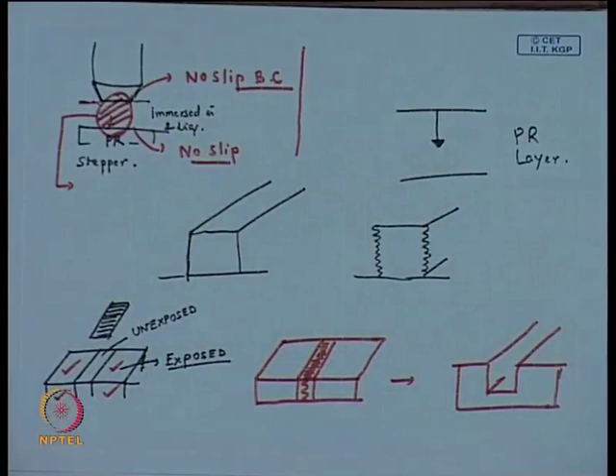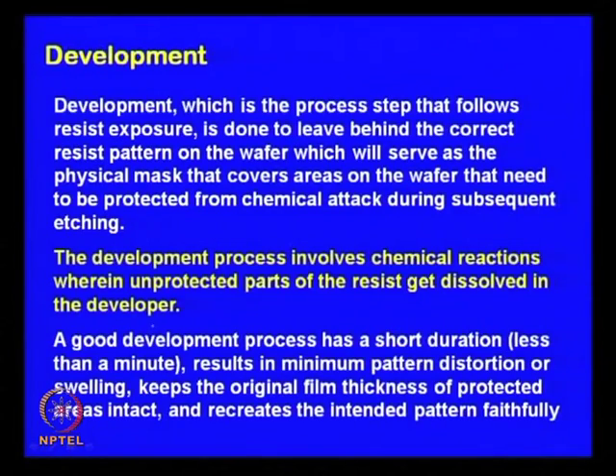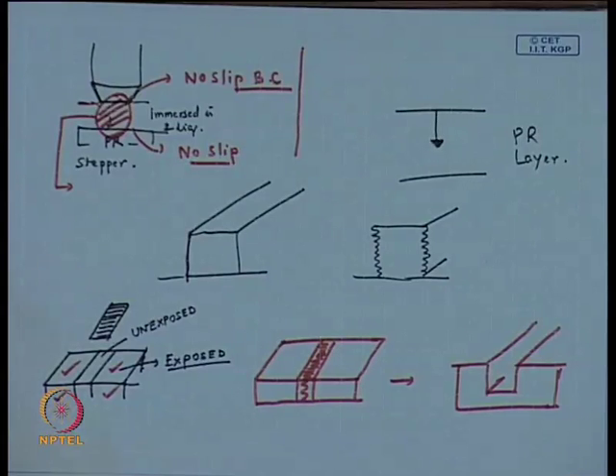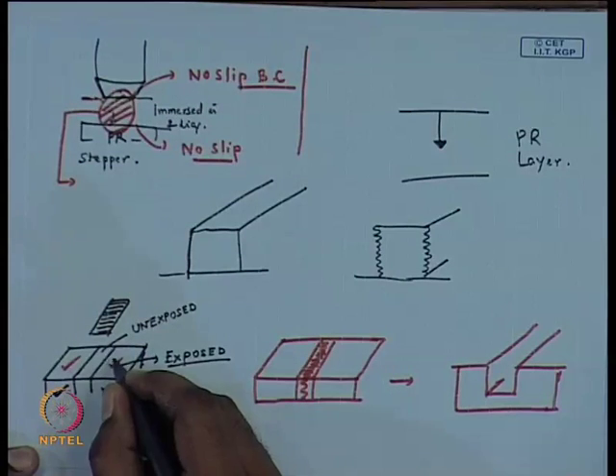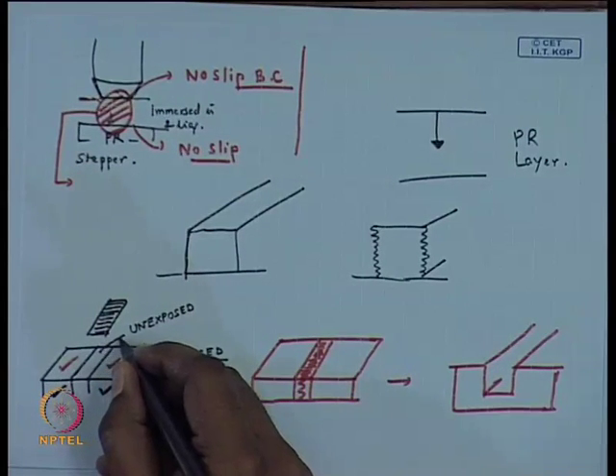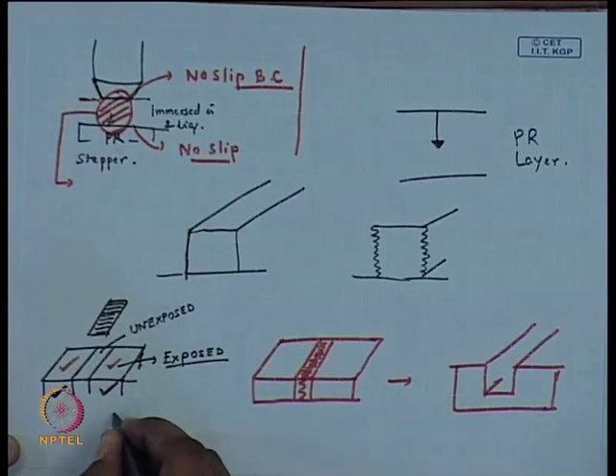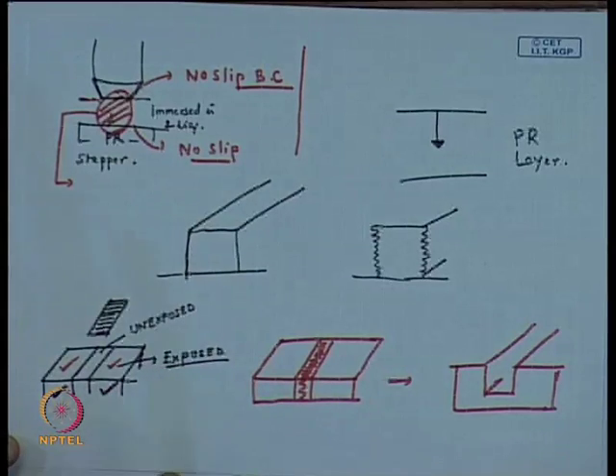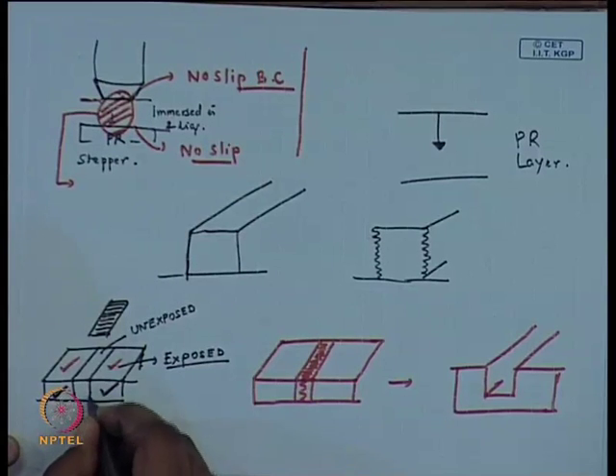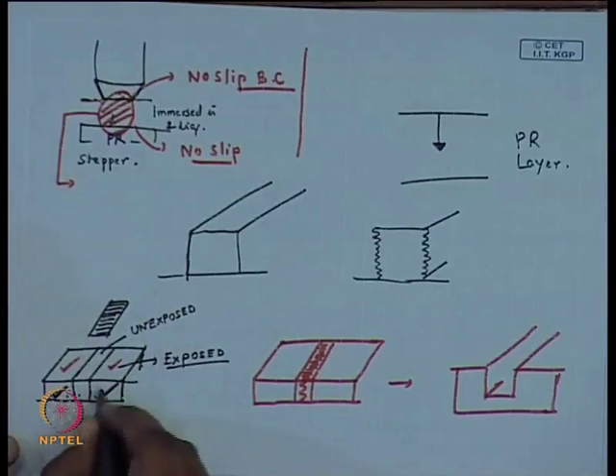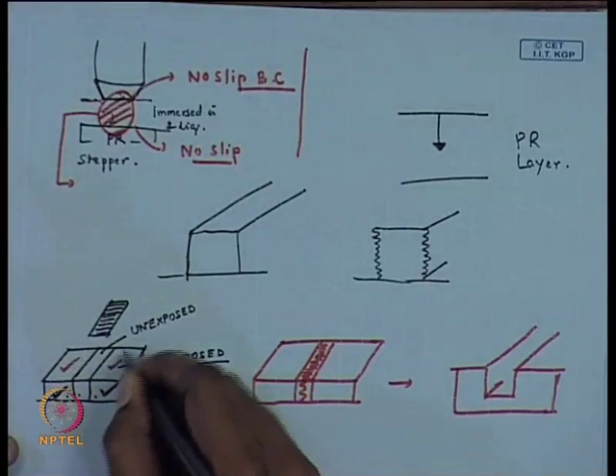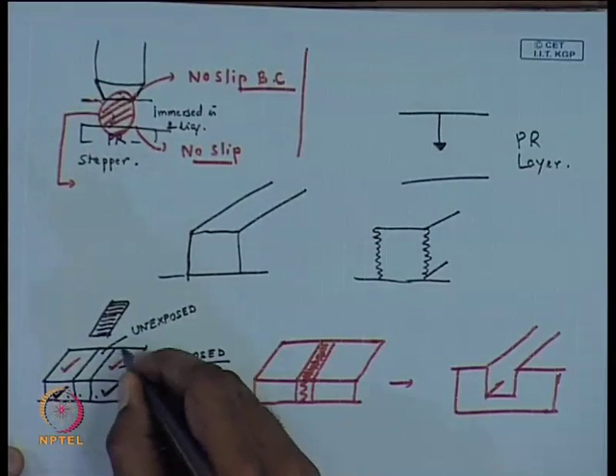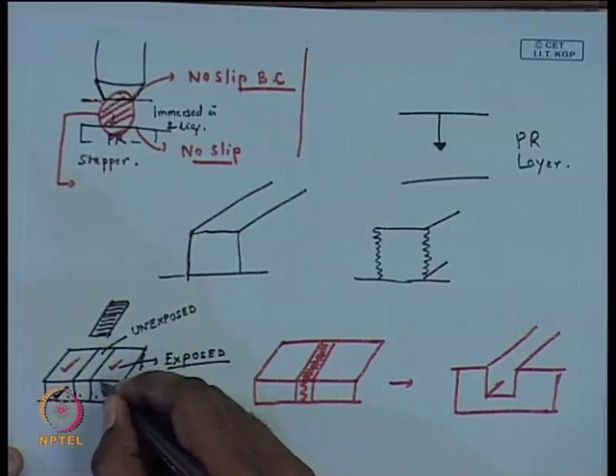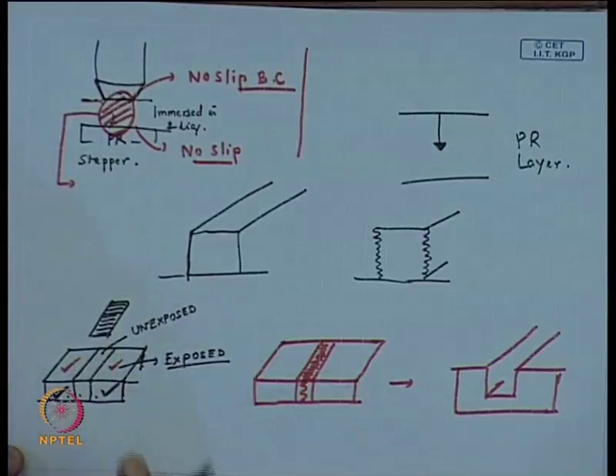There are also quite a few nitty-gritty issues associated with it. It must be understood that a good development process has a short duration, because ideally you would like the developer solution to wash away these areas and you do not want it to affect this particular area, right. Now, the critical thing is that the developer is nothing but a solvent. If you look at these areas, essentially the material is the same, it is the same photoresist. Only part of the photoresist layer has gone through some sort of photochemical reaction and undergone some structural change. However, the material remains the same, and the developer solution you are using is therefore a solvent for this material.